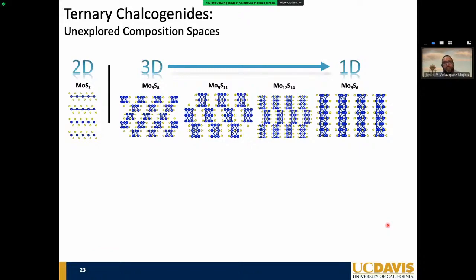Binary 2D metal chalcogenides, we're only scratching the surface here. I know there's been a lot of attention in being able to fine tune the reactivity of these materials. But as you could see here, and actually some of the work that Roald Hoffmann did back in the day, looking at within these material and composition spaces, you could actually play with non-stoichiometries between molybdenum and sulfur and go from an extended structure that has these discrete cluster units all the way to an elongated, sort of like a wire, a slab of molybdenums coordinated with sulfurs. And I'll give you a little bit more information about the structure and how and why this is so cool. Now, I will spoiler alert the following.